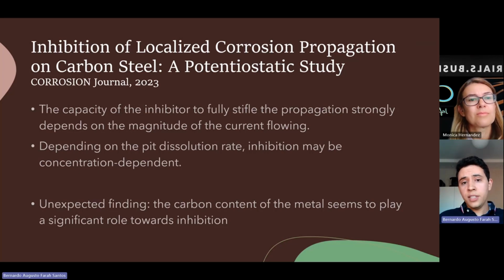And another thing that we figured is that for some of the conditions that we have investigated, the concentration of the inhibitor is quite important for it to be able to stifle or not. So depending on the potential that you are facing on this galvanic cell, because usually when we are dealing with corrosion inhibitors, we tend to use the concentration that is called the surface saturation concentration for inhibitors, and that's the optimal concentration that you will add to your system that will lead to the lowest corrosion rates with the lowest amount of corrosion inhibitor.